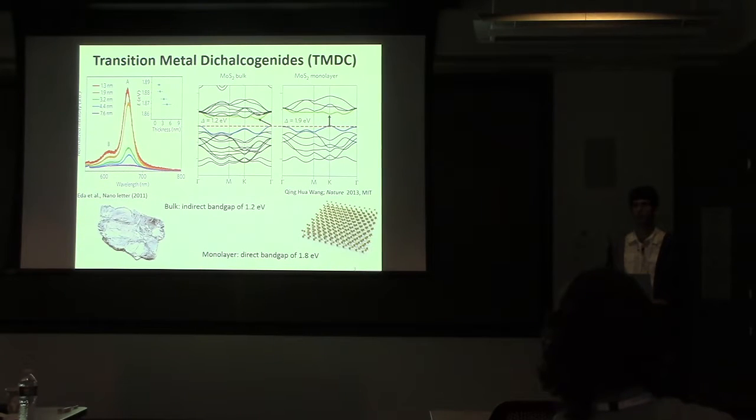for optical applications. Also, what they observed is that as you decrease the number of layers, say from 3 layers, 2 layers to 1, you observe a blue shift of the band gap. So 1.2 electron volt to 1.8. So you can tune the band gap of these materials, which is pretty exciting. And the reason behind this transition of band gaps is the absence of orbital interaction in the z direction between adjacent molybdenum sulfide layers, which causes this quantum confinement effect.